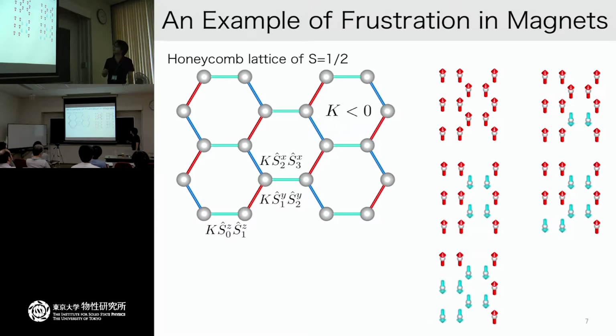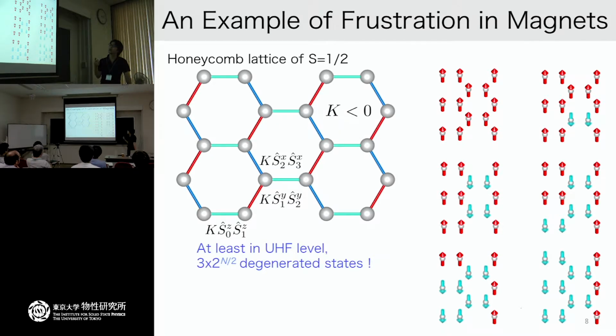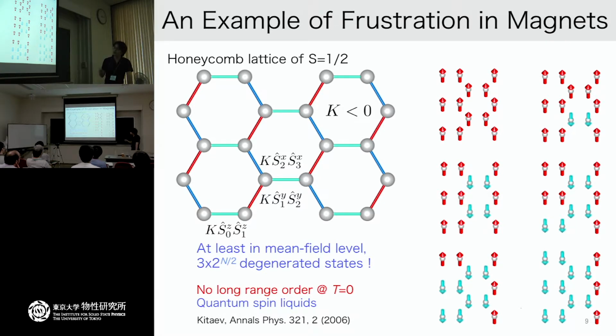So in this sense, you can flip another pair of spins, and another pair, and so on. Then you can generate many classically degenerate spin structures, and this really gives you a macroscopic degeneracy. Only when you introduce quantum fluctuation is this degeneracy lifted. Unfortunately or fortunately, there is some topological degeneracy at the ground state for this Kitaev model, revealed by Alexei Kitaev himself. But anyway, the quantum fluctuation can melt this macroscopic degeneracy, and you end up with several degenerate ground states at zero temperature. This frustration does not come from geometrical frustration, but from the anisotropy of the exchange couplings. It originates from the spin-orbit coupling, or relativistic effect, in the heavy ion systems.